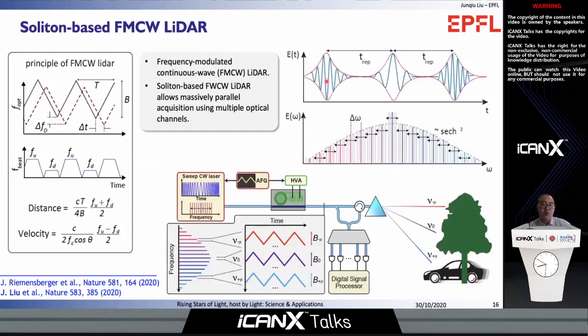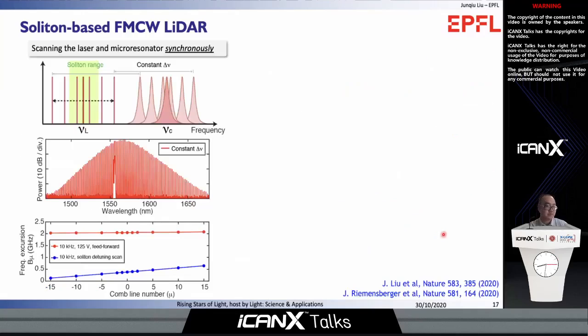Using a soliton microcomb, we can build a massively parallel FMCW LIDAR. By chirping only the pump laser, the chirp is simultaneously transduced to all comb lines. Therefore, by dispersing the comb lines, each of which manifests as an independent FMCW LIDAR, massively parallel data acquisition can be achieved. We use a feed-forward scheme to generate the soliton. In this case, we apply the sweeping signal on the laser and the resonance together. The synchronous tuning is actually realized, and it is important to keep the soliton detuning constant. Therefore, we have a constant soliton spectrum and pulse power.